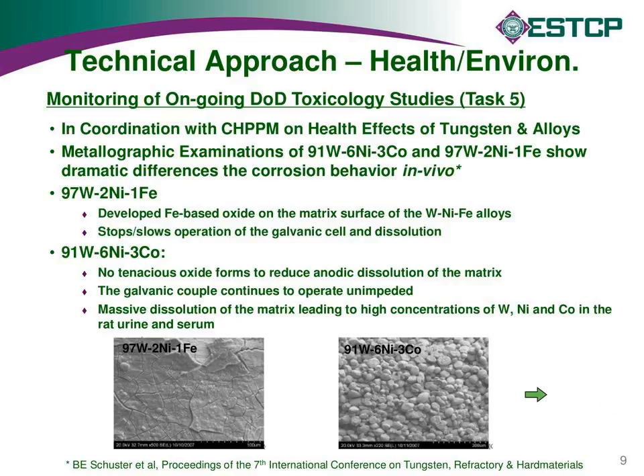And when Brian looked at the pellets themselves, what he saw was, again, with tungsten heavy alloy, it's a composite of these tungsten particles embedded in a nickel, cobalt, tungsten matrix that, at least to a depth of 3 or 4 of these tungsten particles, depth-wise into the microstructure, the matrix had been completely dissolved away. So you basically put a galvanic cell, 2 dissimilar metals in a salt environment in the body, and that nickel cobalt matrix showed up in the bloodstream, in the urine, and nickel was a known carcinogen. The cobalt probably didn't help, but it certainly didn't help limit the amount of nickel that went into solution. So that was a surprise out of those tests initially.